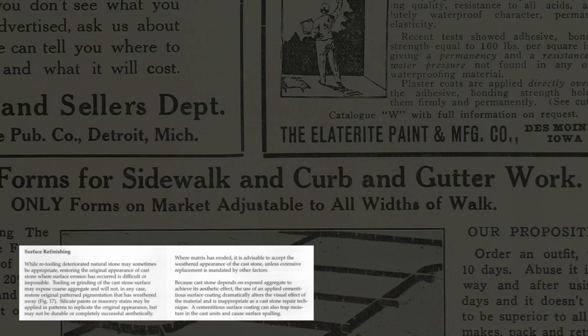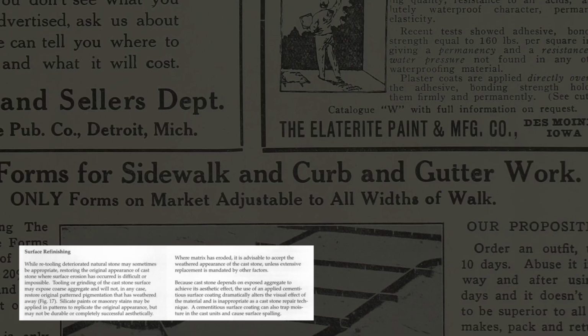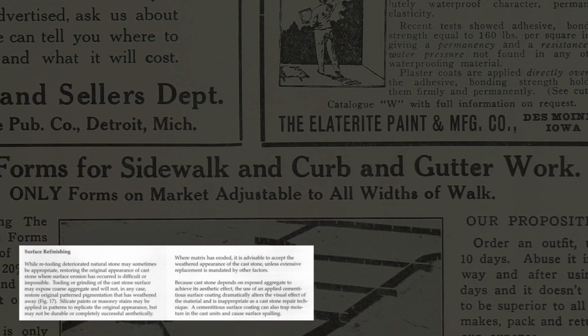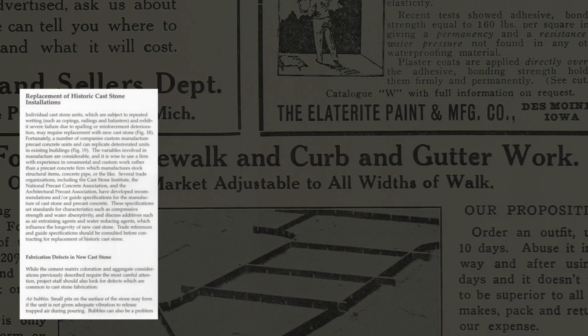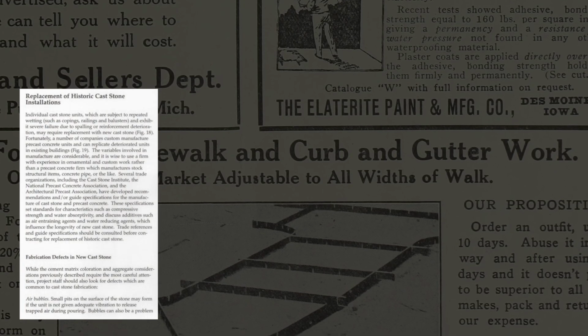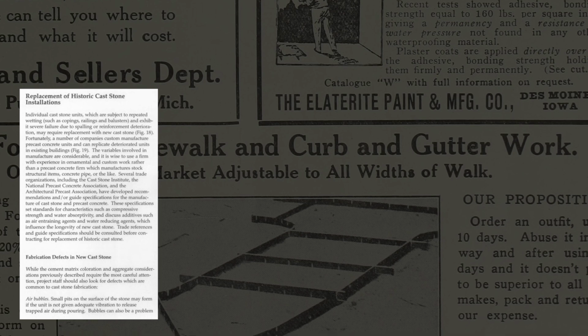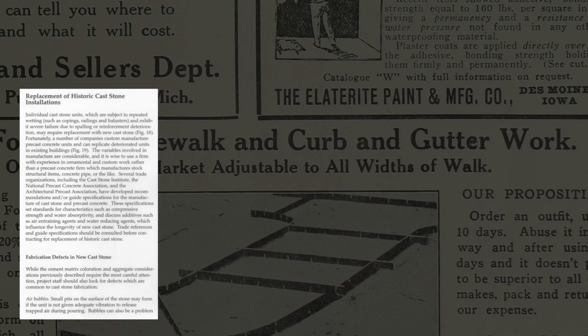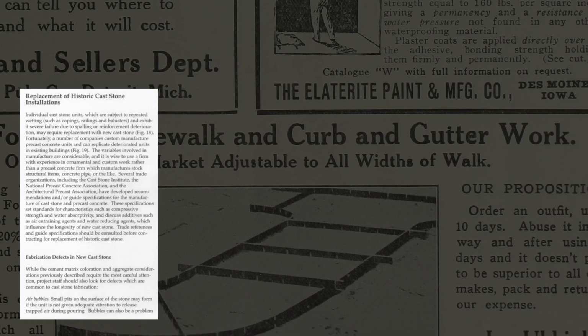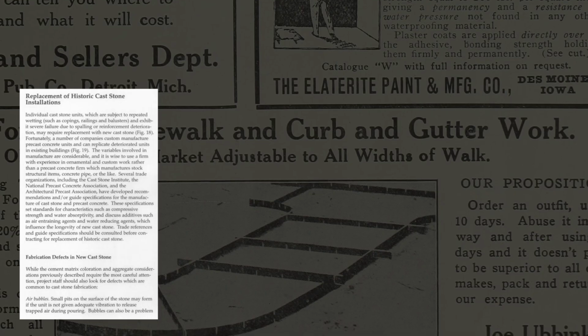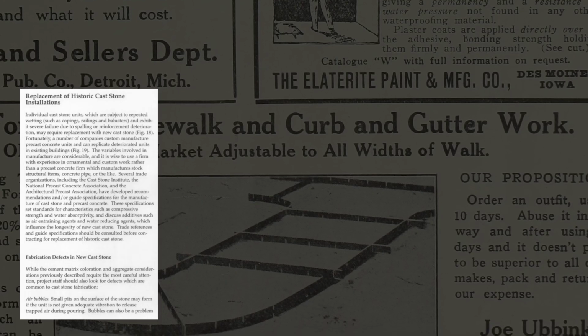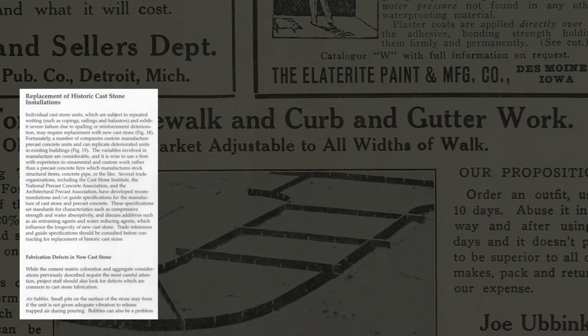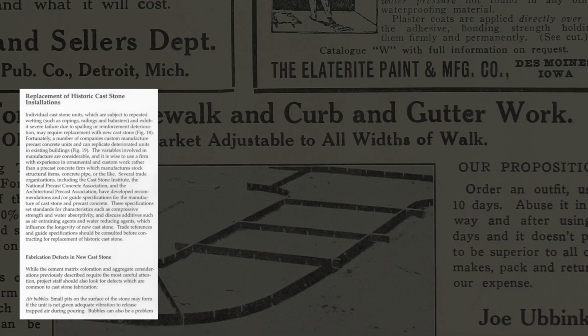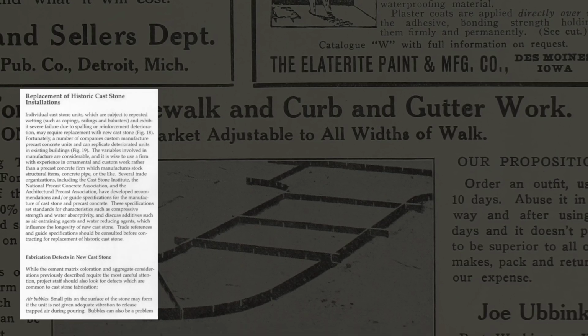A cementitious surface coating can also trap moisture in the cast units and cause surface spalling. Replacement of historic cast stone installations. Individual cast stone units, which are subject to repeated wetting, such as copings, railings and balusters, and exhibit severe failure due to spalling or reinforcement deterioration, may require replacement with new cast stone.